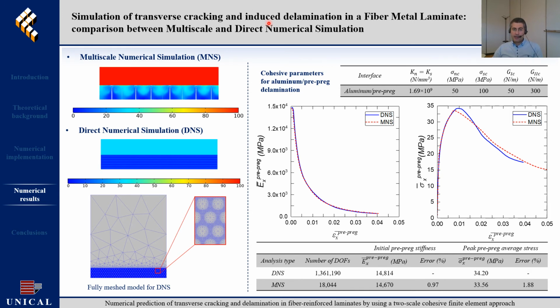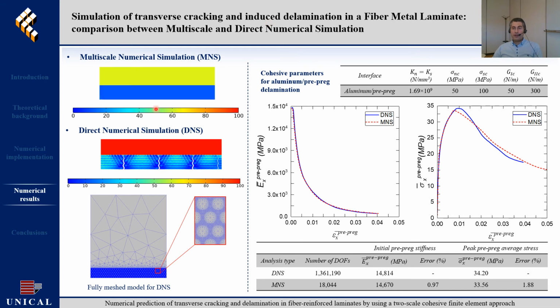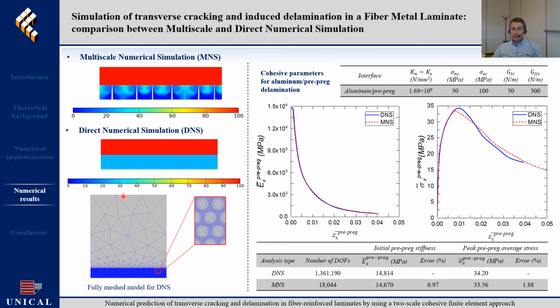As a validation step, the results of this multiscale analysis have been compared with the outcomes of the fully microscopic analysis denoted as direct numerical simulation. In this analysis, taken as the reference, all the microstructural details are explicitly modeled, and both fiber matrix debonding and matrix cracking are included in the same way as in the repeating unit cell analysis.